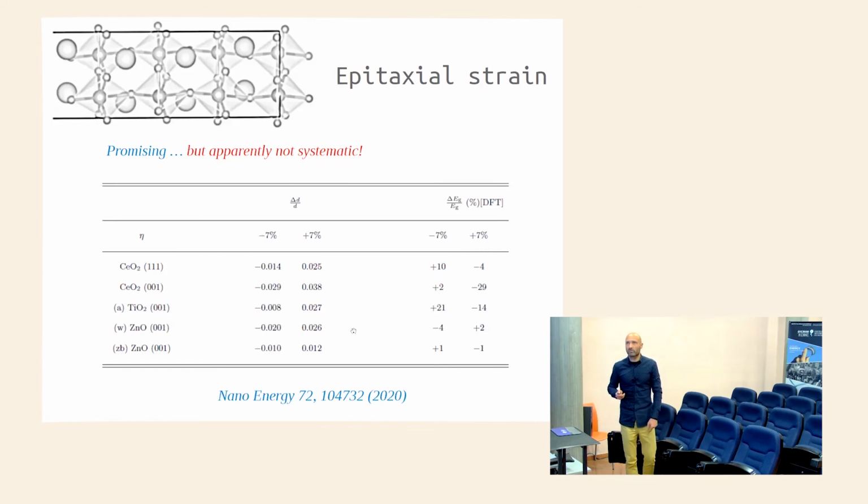And are the following ones. So here I plot how the average distances between the oxygens and the transition metals change as a function of material, as a function of epitaxial stress, right? And we can see that it's always pretty much the same. On the tensile side, we have a larger or a smaller variation, but it increases, whereas on the other side it decreases, right?